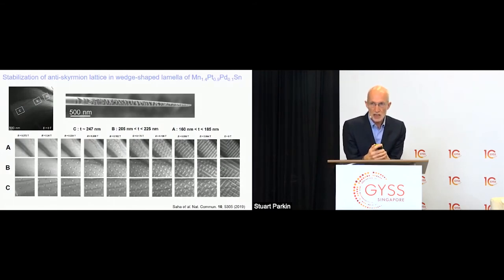Firstly, if we take a series of Lorentz images in different magnetic fields, if you look at the row of images shown in B on the left-hand side, you can see nothing. And that's because if we apply a big enough magnetic field, we will see all the magnetic moments actually become parallel again. And the Lorentz imaging technique is only sensitive to changes in magnetization, not absolute magnetization. But as we reduce the field, you can see in this row B, going from left to right, the anti-skyrmions appearing, until on the very right-hand side, you can actually see a different chiral spin texture, which is a helical spin texture, which is found in zero magnetic field.